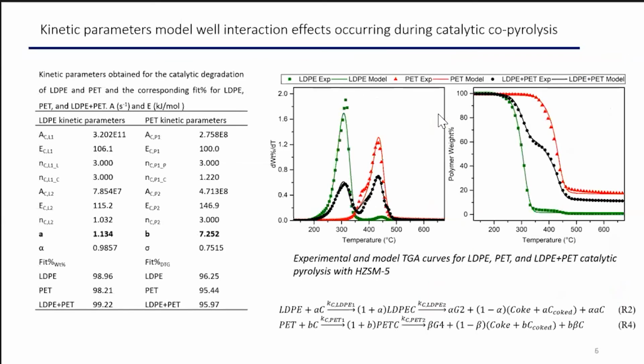So then what we wanted to do now that we had our TGA results is we wanted to apply kinetic modeling to these results, because if we have the kinetics, we can then more easily predict what will happen in larger reactor systems. And so we used a reaction scheme which incorporates a catalytic binding reaction. And what this allowed for was for us to actually model these interaction effects.